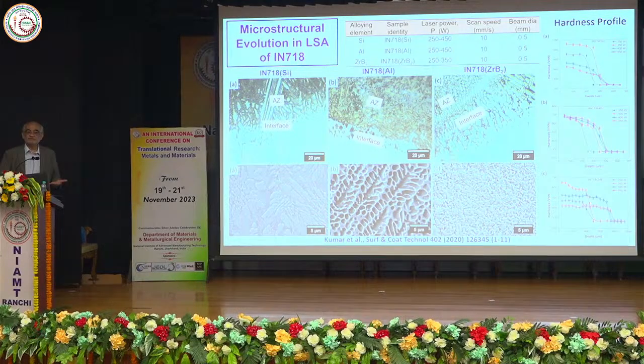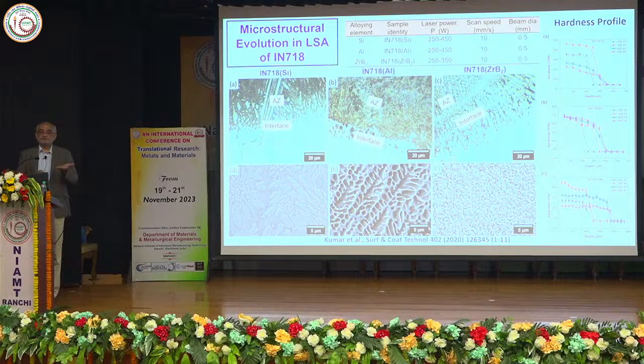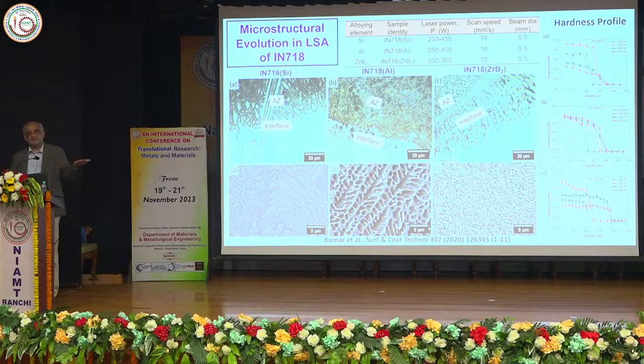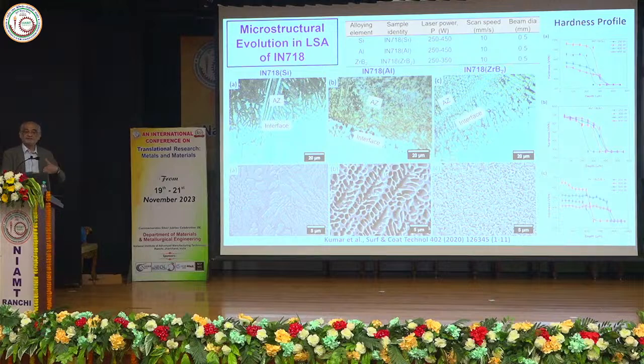So what I'm trying to say is that if you want to deposit or make a thermal barrier coating with zirconia or alumina or whatever, you first need a layer in between which will allow better bonding, like a MCrAlY or any of those multi-component cobalt alloys, which will form a bond coating or bond layer between the base substrate and the top oxide layer. Here you don't need that.